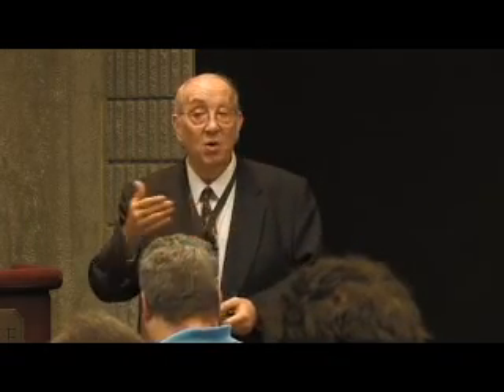I mean, this is almost a textbook picture, if you will. But I find it time after time after time that people with nitriding are not properly controlling either their dissociation levels or their Kn factors, or, for example, in the second stage of gas nitriding. And I want to say this in a polite way, and I'll just use the phrase ignorance, they look at it and don't understand there was a reason why we used dissociated ammonia in the second stage of nitriding versus nitrogen additions during the second stage. There are ways you can use nitrogen, and then there are other reasons for running dissociated ammonia.